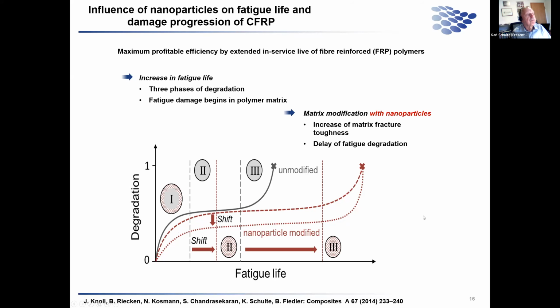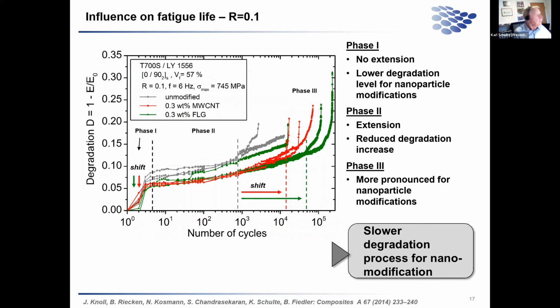We can now show this in a test from various composite materials with carbon fibers T700S, here with an epoxy system. We have the black line, that's the unmodified matrix. The red one has 0.3% multiple wall carbon nanotubes put into the matrix, and we also have few layer graphene, something like thermally reduced graphene, in the matrix. You can see that when we change from unmodified to modified, we have an increase in fatigue life, and the degradation is also better - we have higher degradation here when it is unmodified.